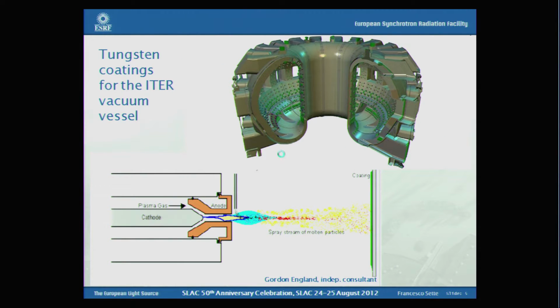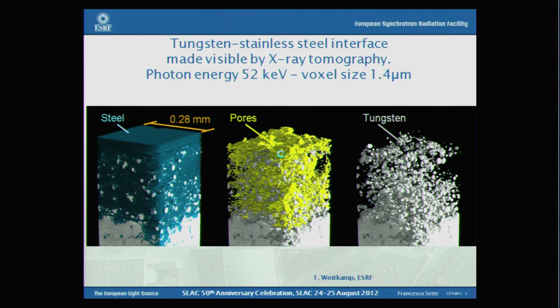And in fact, you can do things which are a little bit more fancy. For example, this is an example of studies associated to how you coat a stainless steel vessel with tungsten. This is the ITER vessel. And then you can go to a synchrotron, and you can do a very careful analysis with resolutions that now are well into the microns or submicron level, to identify the quality of your coating, identify the tungsten parts, the pores, and where the interdiffusion of the materials is, and so on.